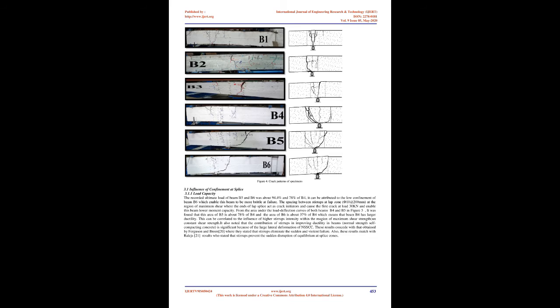The tests showed a remarkable size effect on bond strength. A smaller bar diameter exhibited a higher strength than a bigger one. The bond strength of SCC was found to be higher than that of normal strength concrete. The concrete cover, 4.5 db, where db is the bar diameter, was not sufficient to prevent splitting failure in SCC.